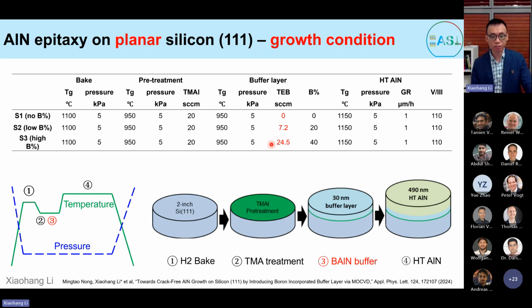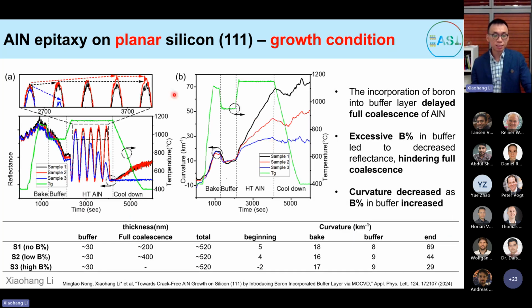So we compare how the boron flow, or the composition of the boron in boron aluminum nitride, affects the sample quality and surface roughness. So this is the in situ reflectance and also the curvature measurement. Okay, so the green one is the temperature, right? Right here, you have the reflectance, and on the right here, you have the curvature of different systems.